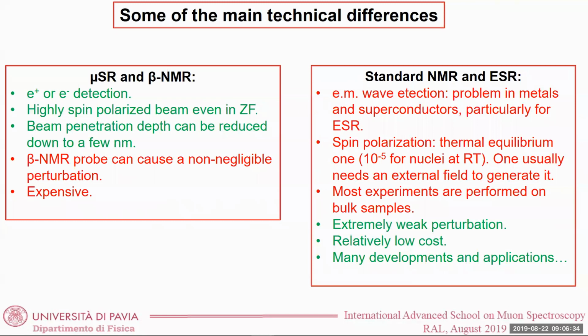The advantage of MUSR and of beta NMR is that they exploit the beta decay, so that you detect either a positron or an electron with certain detectors, while NMR and ESR are based on electromagnetic wave detection. Here there is a D missing. This is a particular problem when you are dealing with metals and superconductors, because you have a problem of penetration depth of a radio frequency, or even worse, of a microwave. So basically, this is telling us that if you're doing an ESR experiment in a superconductor, at the end, it is very difficult because you will probe just a very thin layer of the surface of your material. While with MUSR, we don't have this problem.